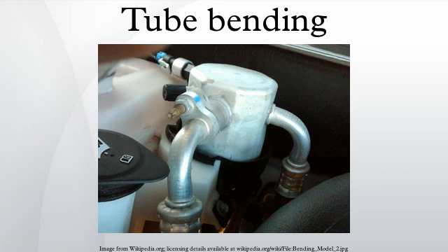CNC rotary draw bending machines can be very complex and use sophisticated tooling to produce severe bends with high quality requirements. The complete tooling is required only for high-precision bending of difficult-to-bend tubes with relatively large OD-T ratio and relatively small ratio between the mean bending radius RM and OD. The use of axial boosting either on the tube free end or on the pressure die is useful to prevent excessive thinning and collapse of the extrados of the tube.